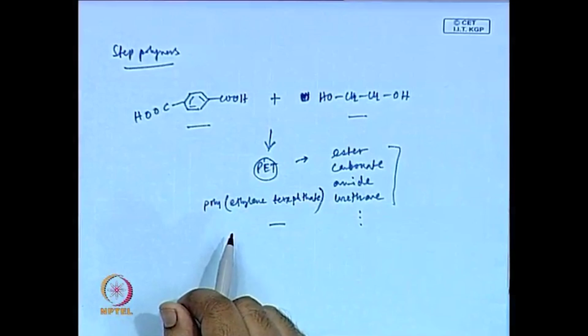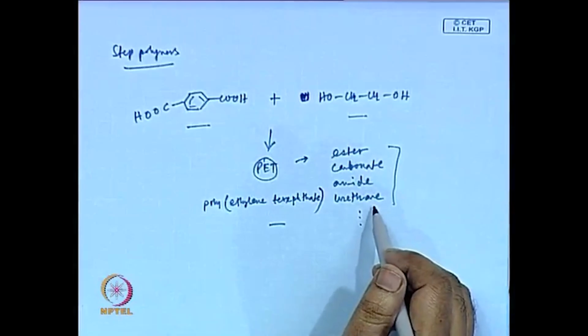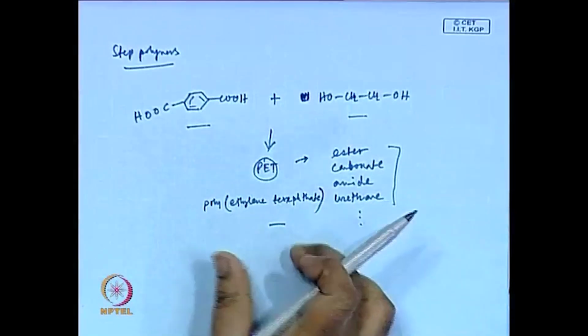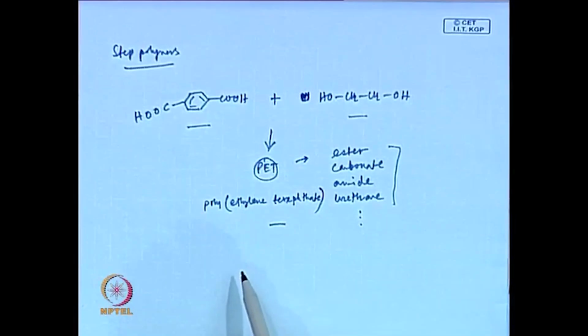other step growth polymers as well, where you have to first identify the functional group or the class to which they belong, and then accordingly you name the polymer. So, a polymer which is formed from say sebacic acid and hexamethylene diamine, acid and amine, you have to name as an amide. So, hexamethylene diamine plus sebacic acid, you will call that polymer polyhexamethylene sebacamide. Okay, you understand?